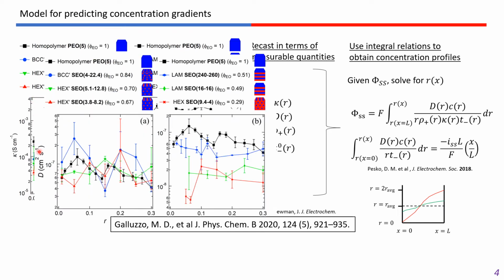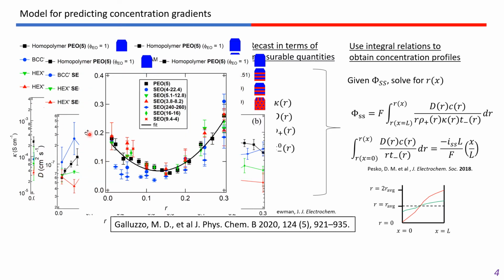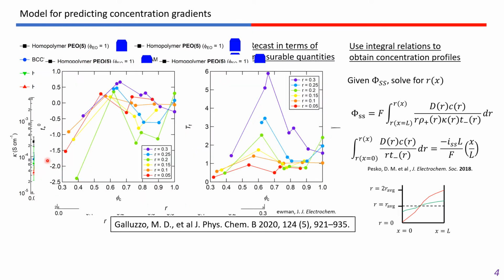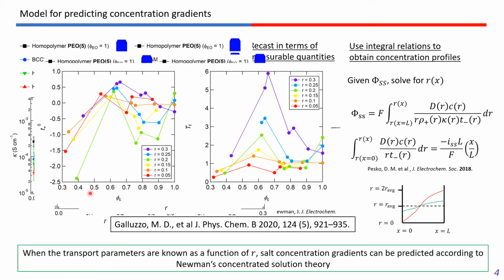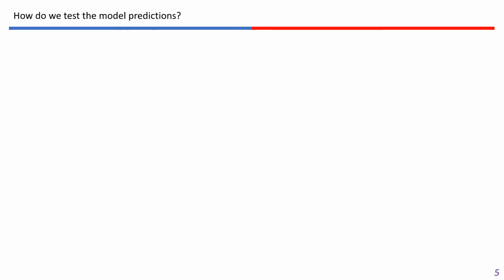And we've also measured the diffusion coefficient, the current fraction rho plus, the transference number, and the thermodynamic factor for all of these systems so that we can use this theory to predict the salt concentration profiles based on Newman's concentrated solution theory. All of these measurements are presented in this paper, but I don't want to spend any more time talking about that and instead move on to discuss how we can test these model predictions.